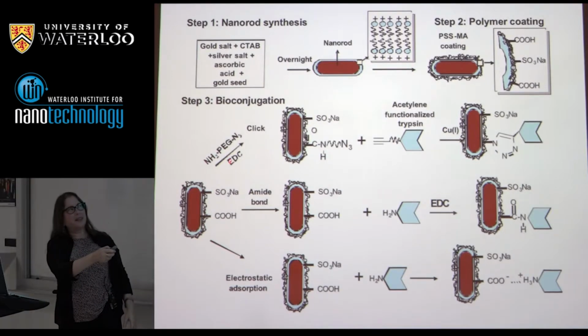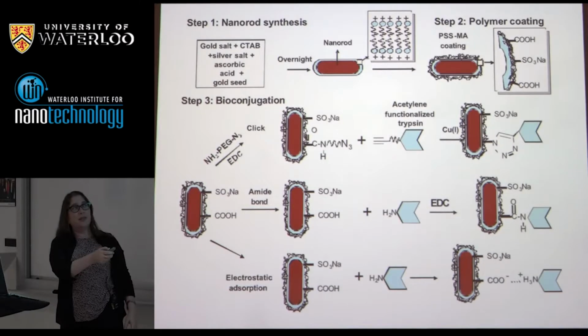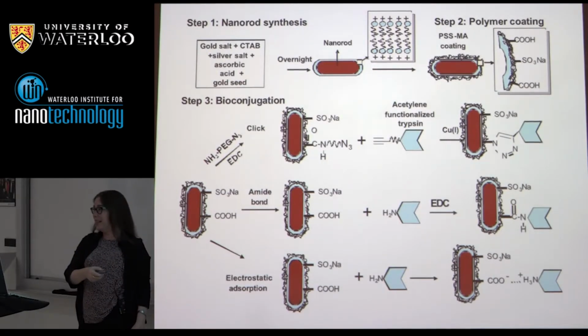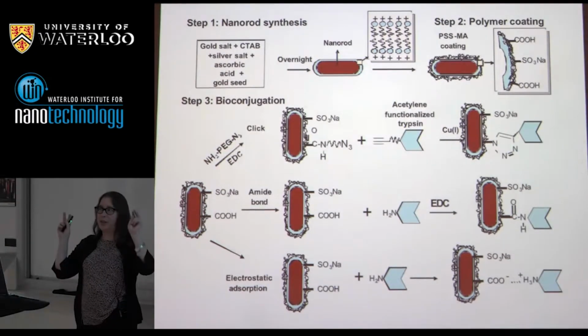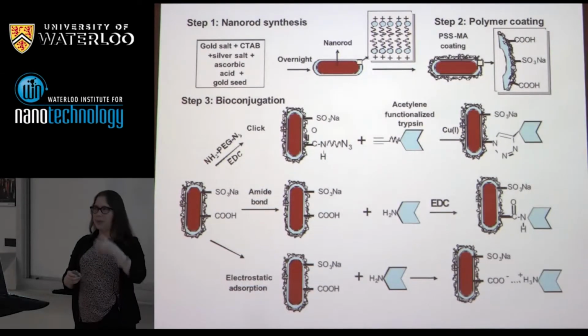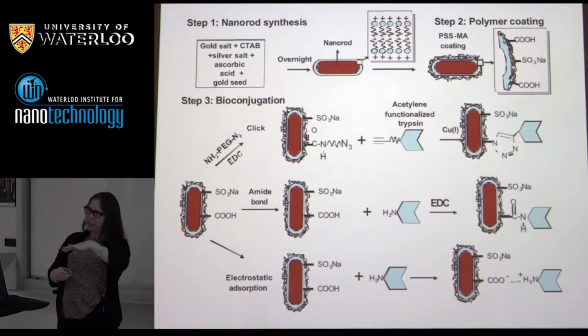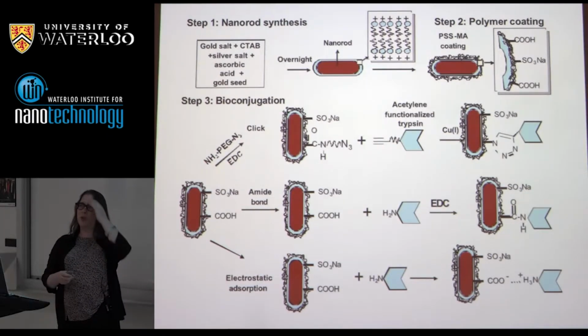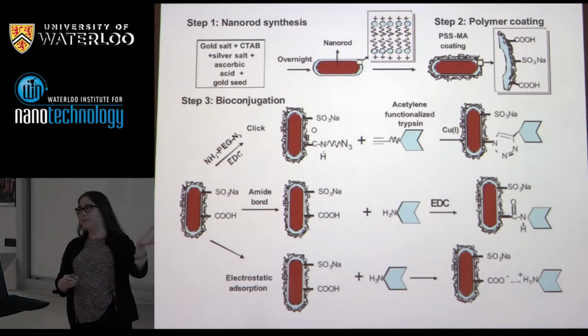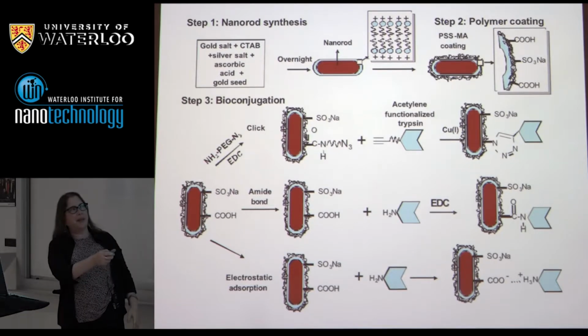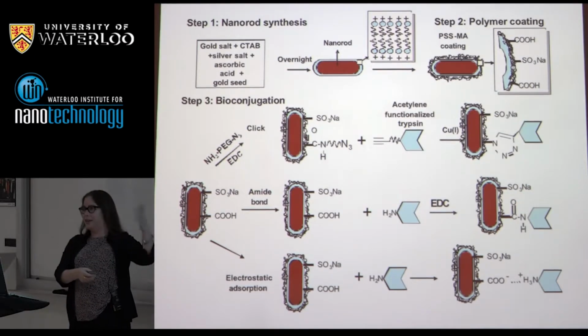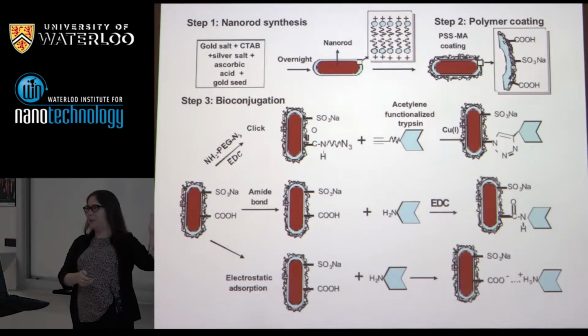But the other thing you could say is, well, the nature of this linker, PEG, polyethylene glycol, everybody knows proteins don't like to be adsorbed to pegylated surfaces, but also everybody knows, why is that? Because PEG is really well hydrated. And if PEG is really well hydrated and you're a protein and you find yourself near a pegylated surface, you are more likely to adopt your native conformation. Okay, so then the argument would be that this system gives us protein that's the right shape, and these two are denatured. Okay, and there is not overwhelming evidence for that either, but there's a little bit.